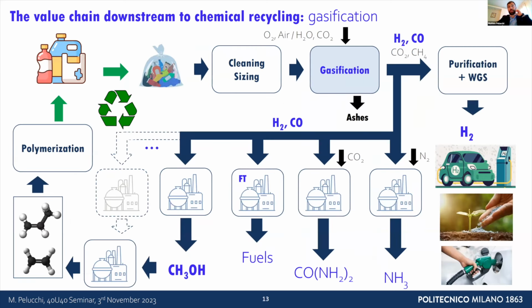Gasification is kind of similar in the pre-treatment. Probably you don't need to get rid of water content because that might be helpful. You get into your gasifier and produce syngas. If you want to increase hydrogen yields, you make a water gas shift reaction, which provides hydrogen. Otherwise, you can live with syngas.